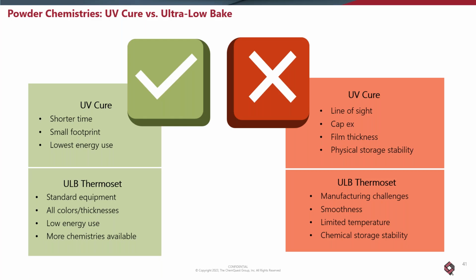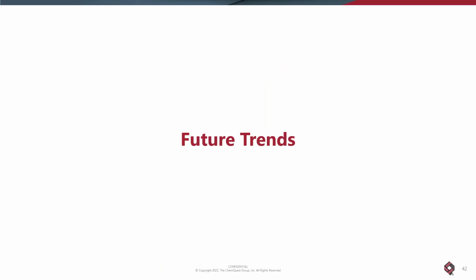Like I mentioned with the UV cure, it's line of sight, film thickness, physical storage stability. Sometimes you're in a first adopter type situation. With really low temperature thermosets, it's more in the processing of the powder coating through the extrusion process where you really have to watch what you're doing.